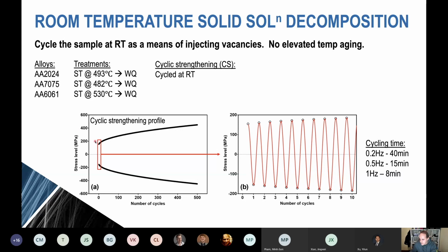Now, during the process, the material strengthens because we have this decomposition of the solid solution, and that's why we design a stress profile that increases. So this stress profile is really designed to control the plastic strain amplitude during cycling. And we would typically do something like 500 cycles. And if you do it at 1 Hertz, that means less than 10 minutes. If you do it at 0.2 Hertz, it's about 40 minutes. And so these are very, very short times compared to the traditional treatment time used for the elevated temperature aging of precipitate hardened aluminium alloys.